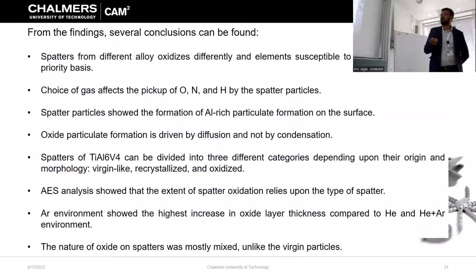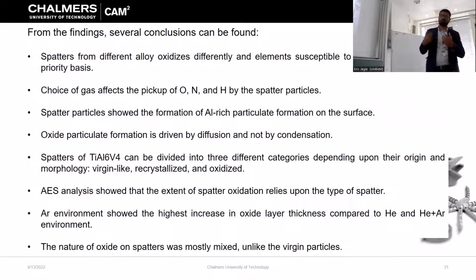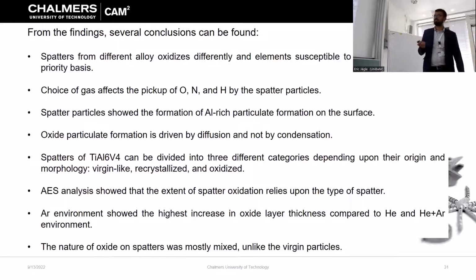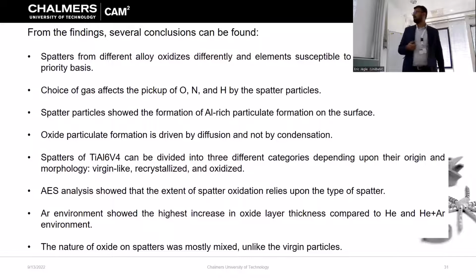And spatters of Ti6Al4V can be divided into three categories that we identified: virgin-like, which are not much affected, recrystallized, and oxidized. AES analysis shows the extent of spatter oxidation relies upon the type we identified. The argon environment showed the highest increase in oxide layer thickness as compared to helium or the mixture. And the nature of oxide on spatters was mostly mixed, as compared to the virgin particles.